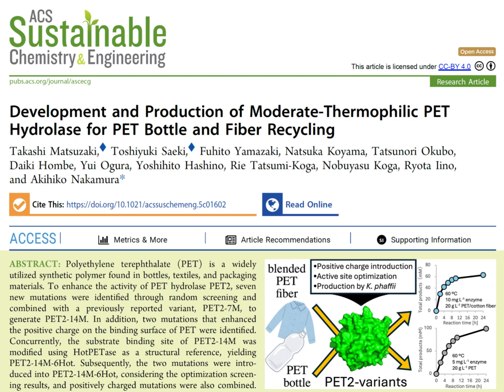Right, but here's where PET2-14M really shone, when they halved the enzyme concentration using only 2.5 milligrams per liter. Making it potentially cheaper. Exactly. PET2-14M still degraded a significant 50% of the PET in 24 hours. LCC-ICCG, at that lower concentration, only managed 26%. So PET2-14M is much more efficient when you don't use as much enzyme. Precisely. It highlights its superior efficiency at lower, more economical enzyme loadings. You need less of the expensive stuff to get the job done, potentially. That seems like a big deal for industrial use. It is. And it also brings up that interesting point about temperature.